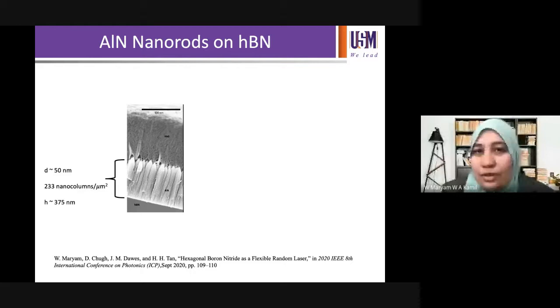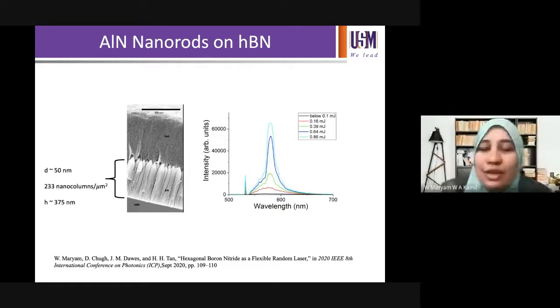Now, the issue is aluminum nitride is deep UV, so it's very hard to excite the deep UV. Therefore, it was not possible to actually make the aluminum nitride become a gain medium. But what we did was we put in rhodamine 6G. So we had a dye to see if we can get lasing. Okay, if this aluminum nitride can become scatterers for random lasing to occur, and yes, we actually observed that.